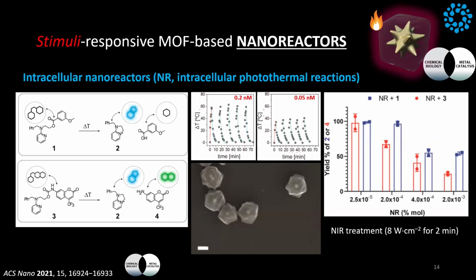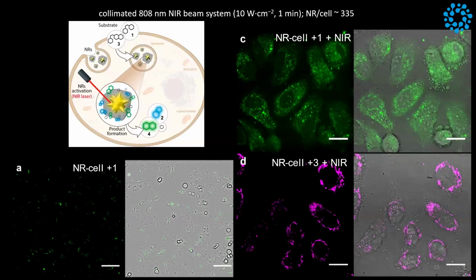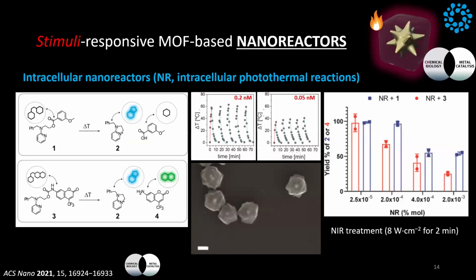And then he prepared some molecules, 1 and 3, so that typically you can close them and make them fluorescent. But this kind of reaction, this thermocyclization, requires 90 degrees, organic solvent, overnight. So my challenge was, can you do that inside a living cell? And my idea is that I have something that is going to be very hot, a golden star. I will put some light, and I will create a very high temperature gradient where I'm able to do these reactions.